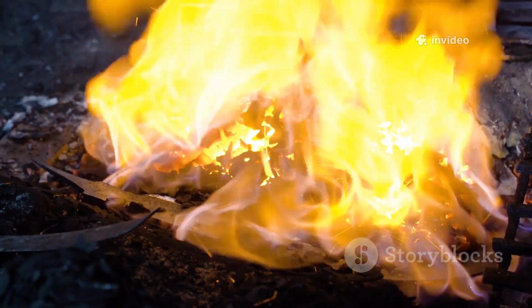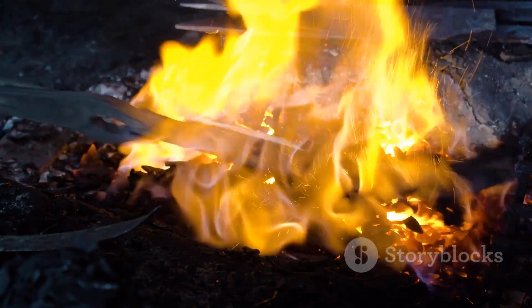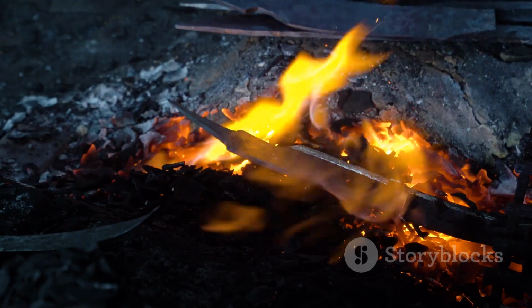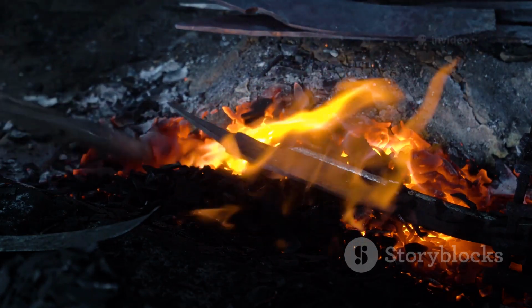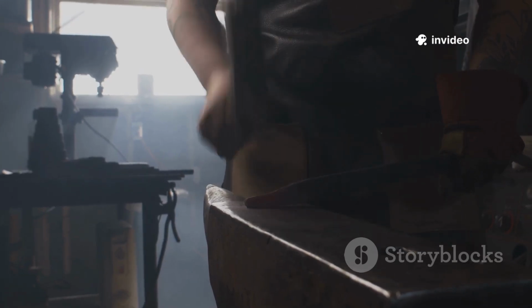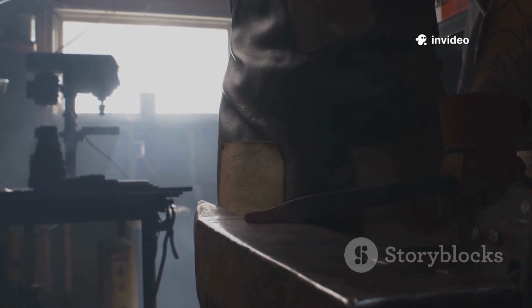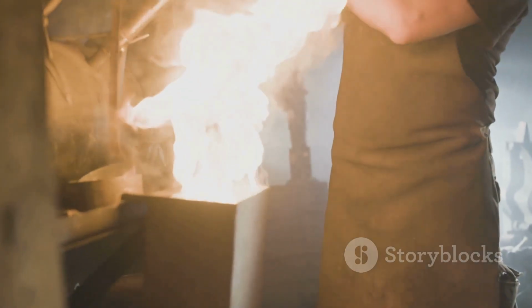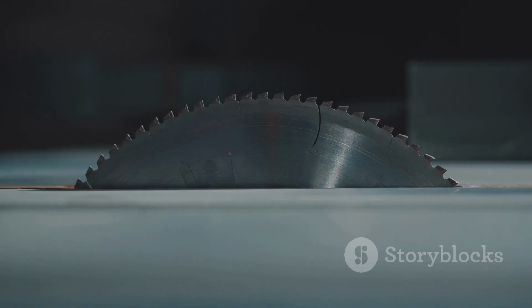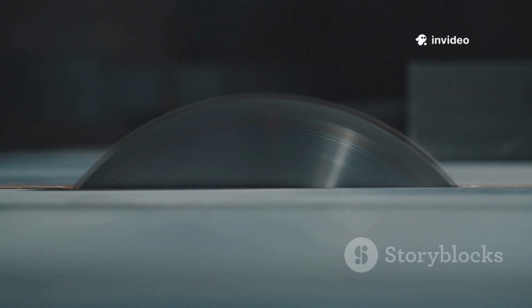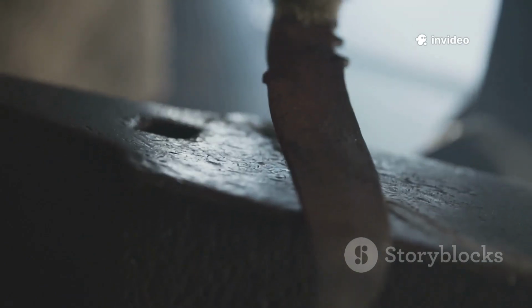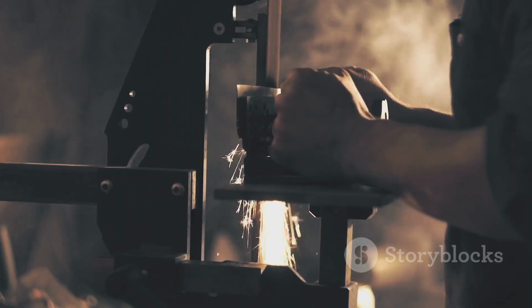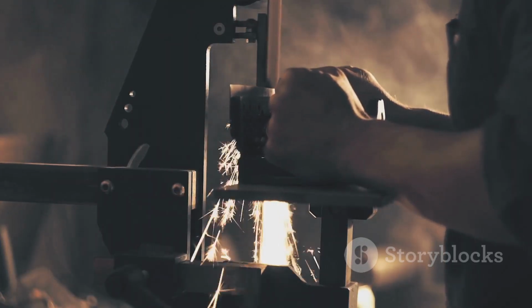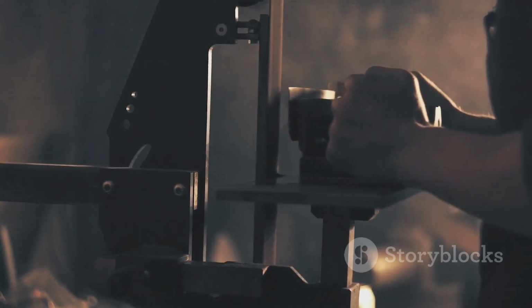The glowing hot blade is plunged into a liquid, which is often a special type of oil, though water or even air can be used for different steels. This sudden, dramatic drop in temperature is a huge shock to the steel system. It doesn't have time to cool down slowly and form soft crystals. Instead, the carbon atoms get trapped within the iron structure, creating a new, very hard and brittle crystal structure called martensite. The blade is now incredibly hard, so hard that a file would skate right off it without cutting in.